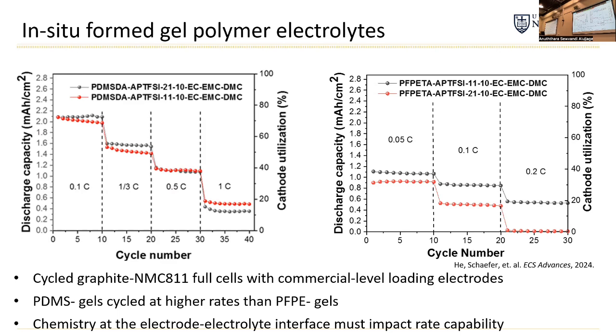The other thing we found is that despite the fact that the PDMS and the PFPE gels had roughly the same bulk ionic conductivity, the PDMS-based gels had way better rate capability. If you do the math, you'll find that the rate capability was way lower than you would expect from the bulk ionic conductivity in both cases, but the difference was much more substantial with the perfluoropolyether. We also did a lot of impedance studies and made lithium metal cells, and the same thing held: the perfluoropolyether interface with lithium metal is much more resistive. We can say that the chemistry of the electrode-electrolyte interface is really important, and it really impacts rate capability. By adding in these polymers, even though we often imagine that polymers are inert, it really impacts the surface chemistry and the SEI. That's something we should keep in mind in the future.